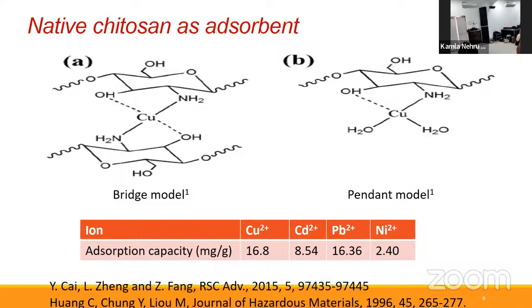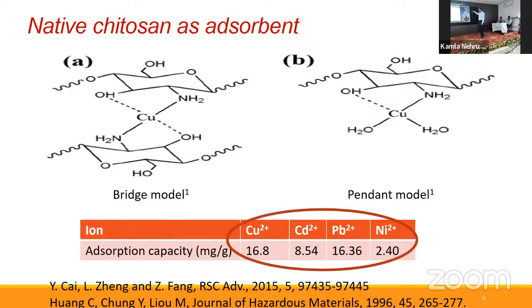When we talk about chitosan as a water treatment agent, the native or pure chitosan can be used as an adsorbent, and it has been reported in the literature for more than 20 years that it can be used for capturing various metal ions because of the OH and NH2 functionality, which have lone pairs that can form coordinate bonds with various metal ions. It is possible to capture many metal ions of environmental importance, including cadmium, lead, nickel, copper, etc. All of them can be captured by complexation with chitosan's NH2 and OH functionality. Two models are reported in the literature, the pendant model and the bridge model, where the metal ions get trapped in the chitosan matrix.